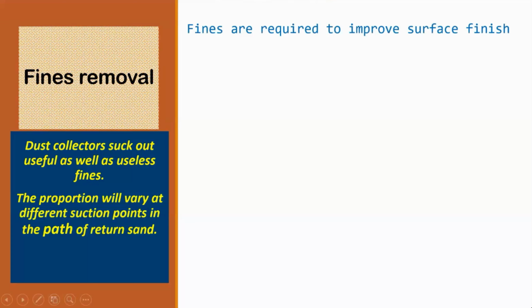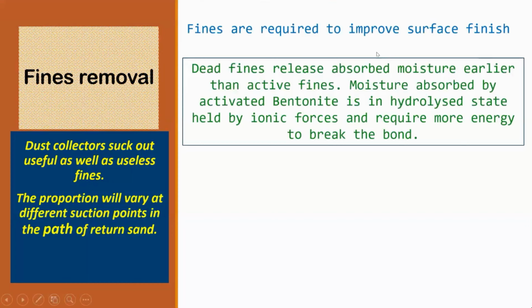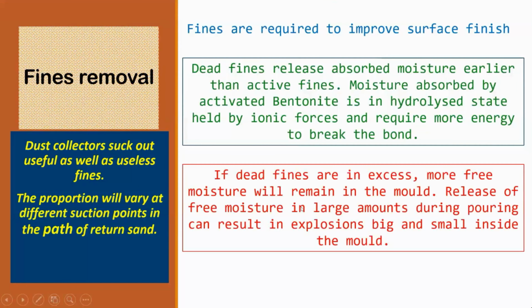The fines are required to improve surface finish because they occupy the spaces between the sand grains, whereas dead fines release absorbed moisture earlier than active fines. Moisture absorbed by the active bentonite is in a hydrolyzed state, held by ionic forces. So they require more energy to break the bond. If dead fines are in excess, more free moisture will remain in the mold. Release of free moisture in large amounts during pouring, that is 1 gram, we said, 1667 cc of steam, can result in explosions, big and small, inside the mold. So judicious reuse of fines can benefit the process.